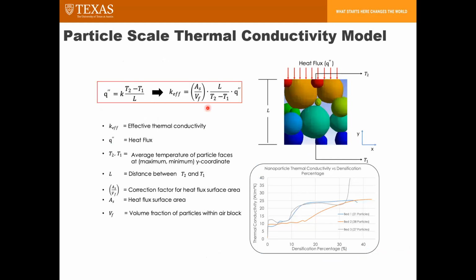The thermal simulations use a 1D approximation of steady state heat flow, where heat flux is applied on one end and the other end is held at a constant temperature. And so to calculate the thermal conductivity, we use the 1D approximation of heat conduction using Fourier's law, but modified to account for the non-uniform surface area across the primary direction of heat flow. And so using the sintering simulation and combining that with this, we're able to get curves that relate the thermal conductivity to the density of the powder bed.